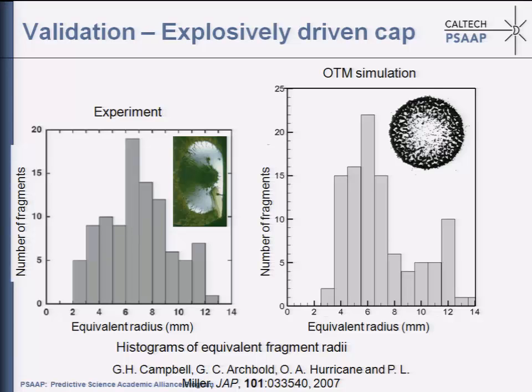And you actually see a more or less reasonable correlation, for instance regarding the mean size of the large fragments. There are 2 peaks in the distribution, both in the experiment and in the simulations. I really have no idea why there are 2 peaks. Maybe it's just a complete fluke, but you count your blessings. And generally, perhaps the key point is that we can make contact with engineering testing, macroscopic test data, in this case from the experiment of Campbell et al.